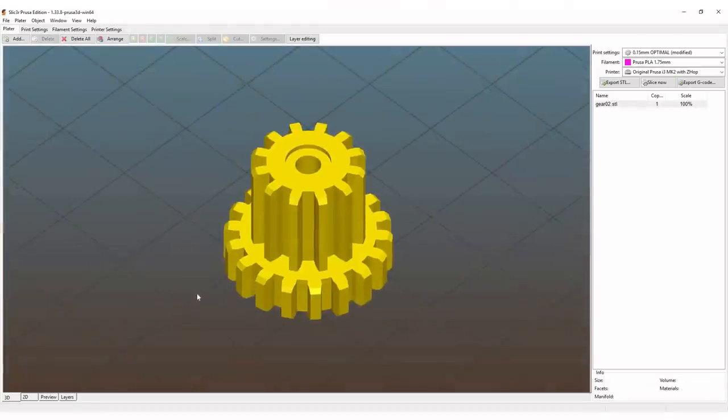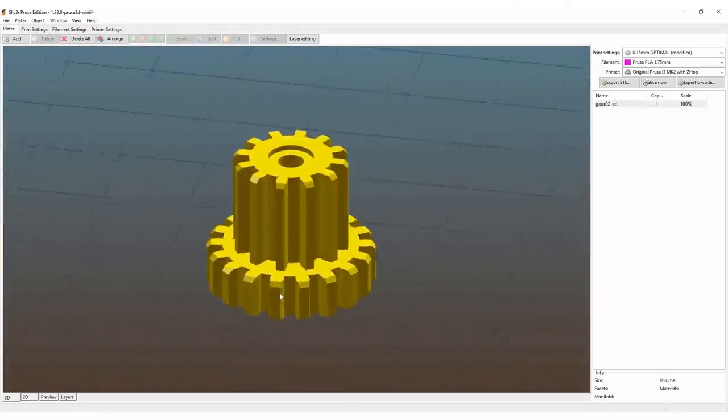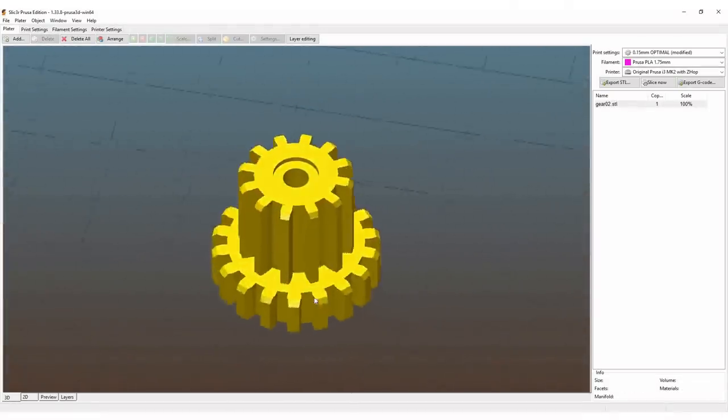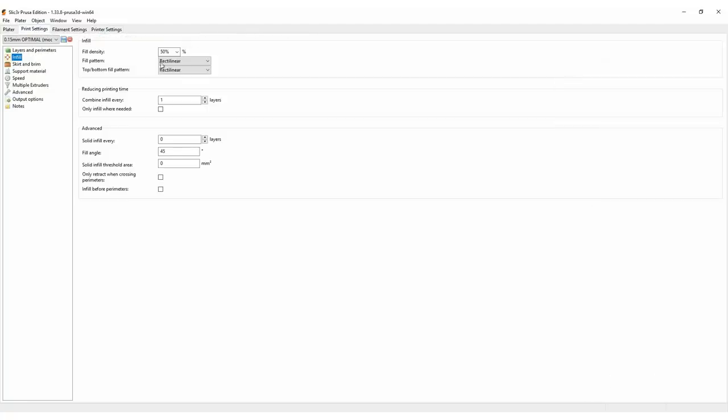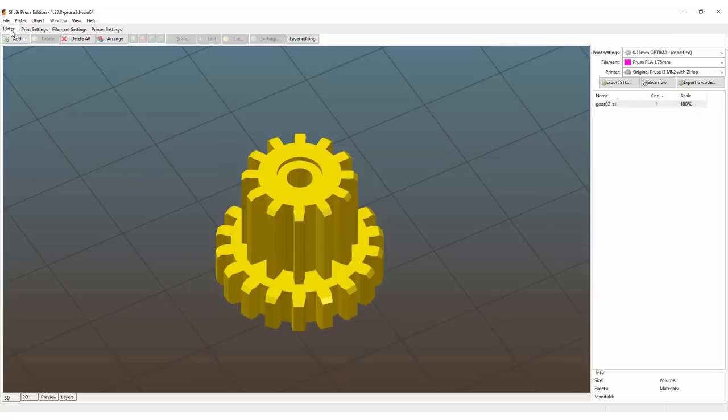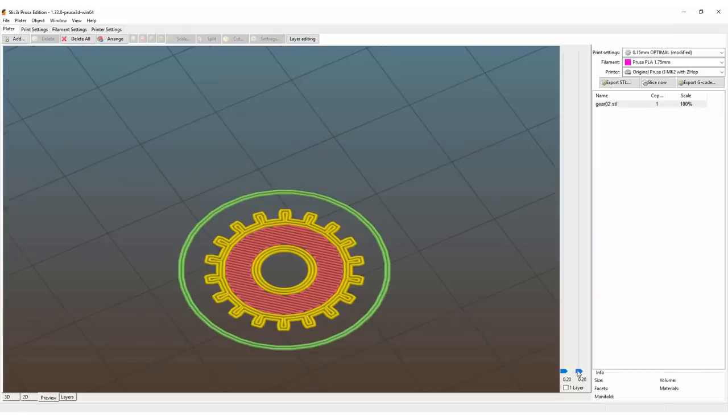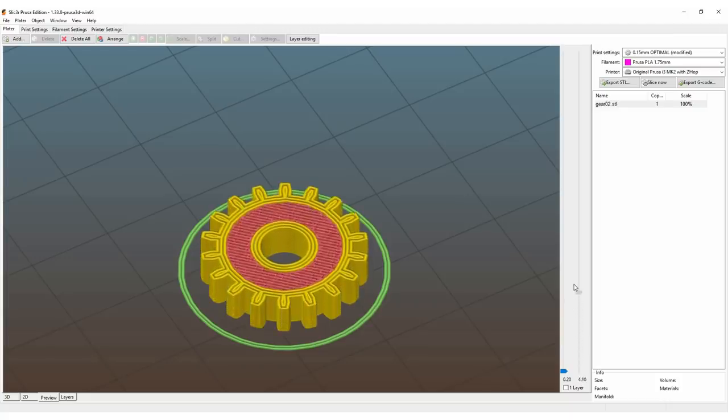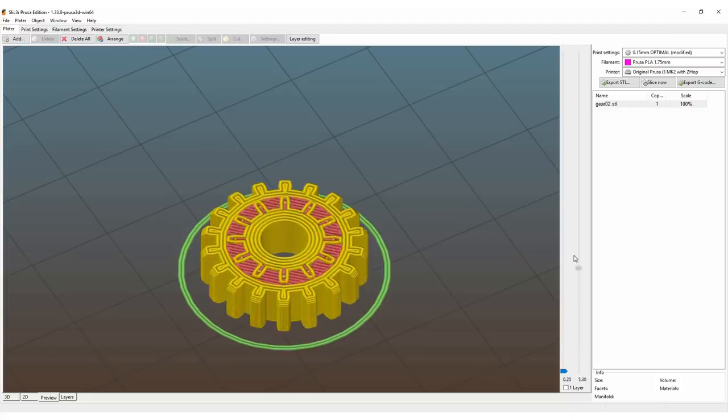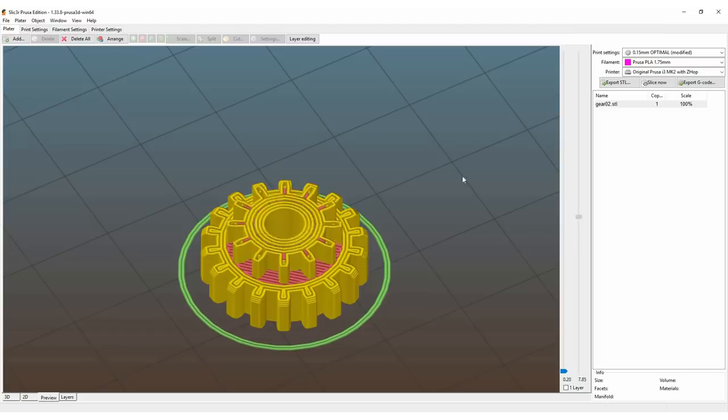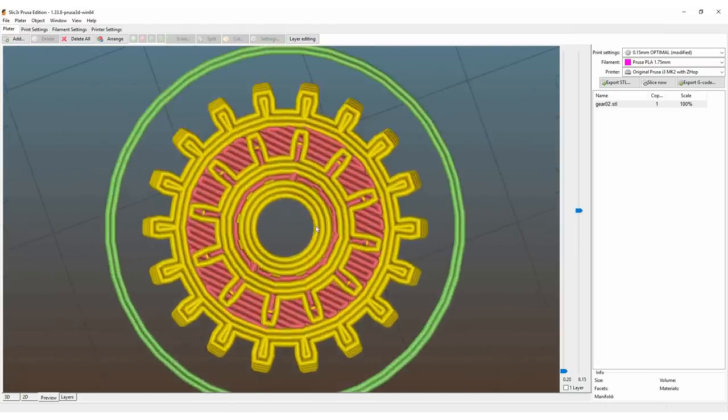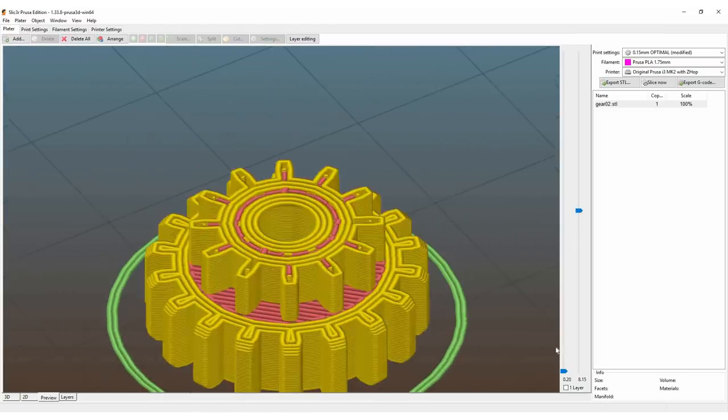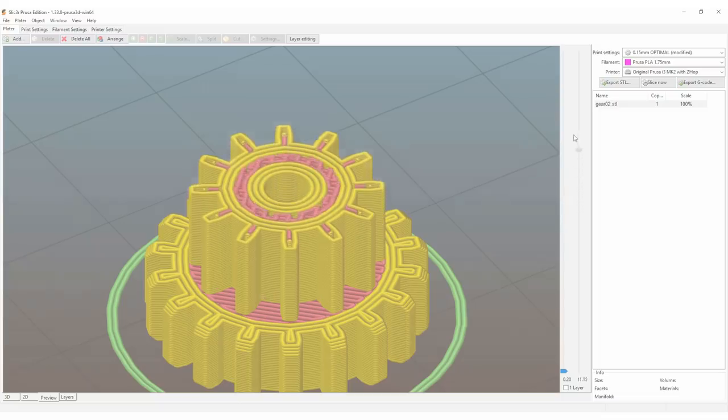I printed the gears with 50% infill, four perimeters at a layer height of 0.15mm. I often see people printing their parts at 100% infill if they want to have a strong part. In 99% of the cases this is not necessary since the maximum stresses will be on the outside of your part. Increase the number of perimeters if you want a stronger part and don't work with any infill values of more than 50% if you don't have a good reason. Using 100% infill will only screw up the tolerances of your part, but it will only increase the strength slightly in most cases.